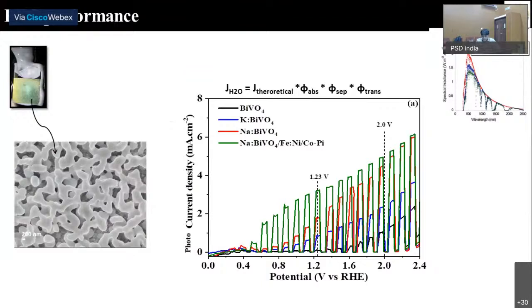So starting with my work, this is the typical electrode coated with bismuth vanadate, and this is the surface morphology. We can see that the surface is porous and it has very good wettability also. And with the doping, the surface morphology doesn't change. Now, if you see the water splitting behavior that we correlate corresponding to the photocurrent density, we measure in a 3 electrode setup. The bismuth vanadate, shown in black, has a very low PCD, that is photocurrent density. That means its water splitting performance is very poor.